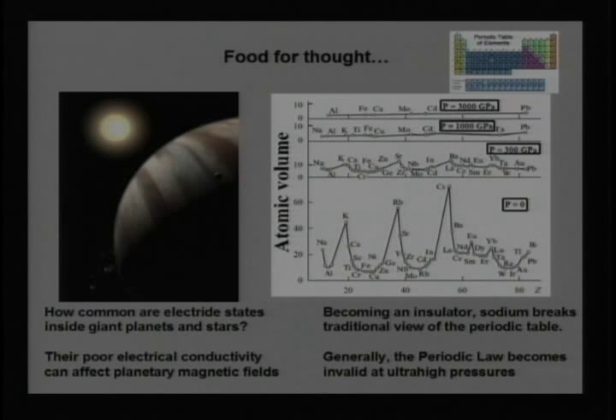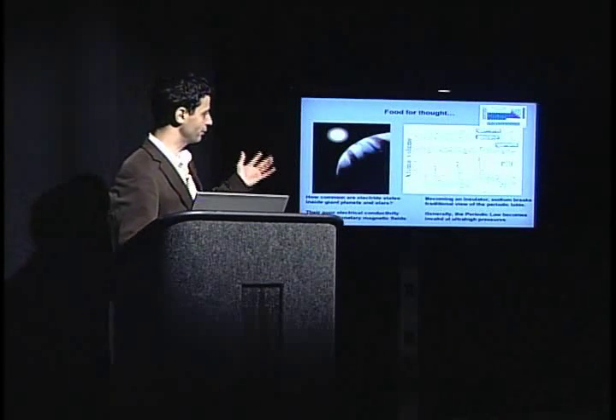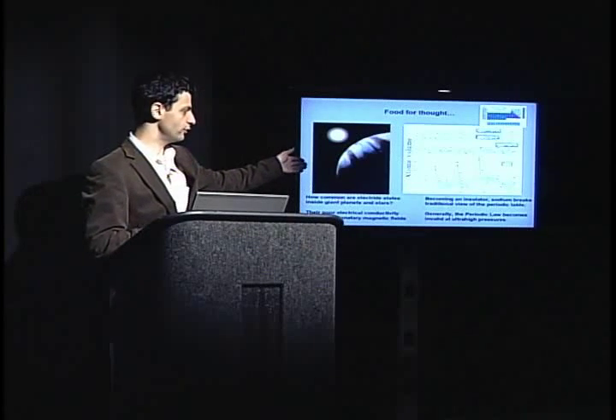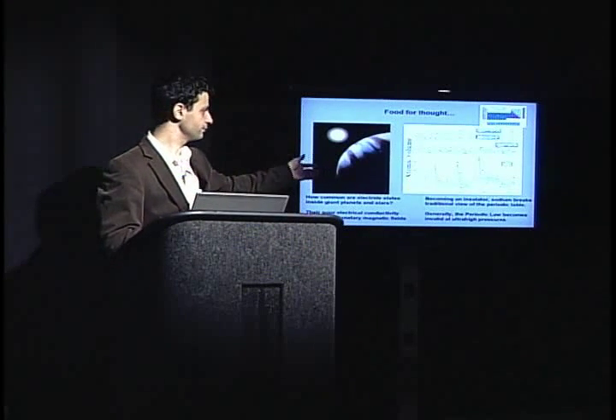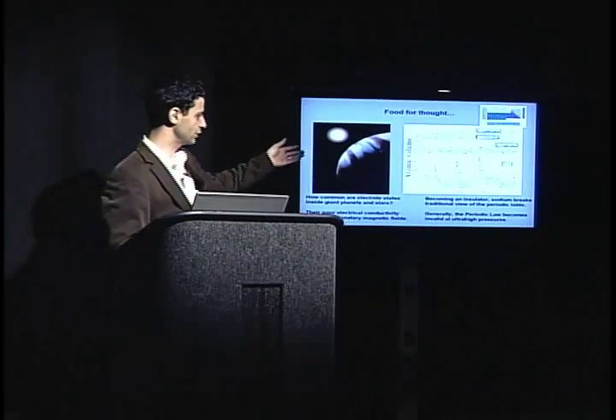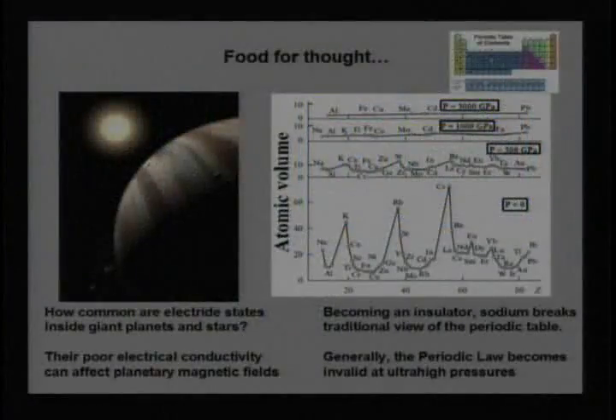So, what is the outlook of this work? What is the significance? We have shown that if you compress even a very good metal, you can get an insulating state. This is what several people expected before, people like Ashcroft and Neaton. But this is something that we have proven with experiments, and observed to an extreme extent. We transform to a wide gap transparent dielectric. The same phenomenon can, in principle, occur in other elements. And one can imagine that in some giant planets and in stars, where atoms are very strongly overlapping with each other, you can also form perhaps similar dielectric states.